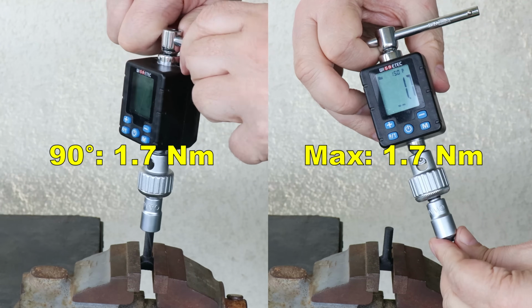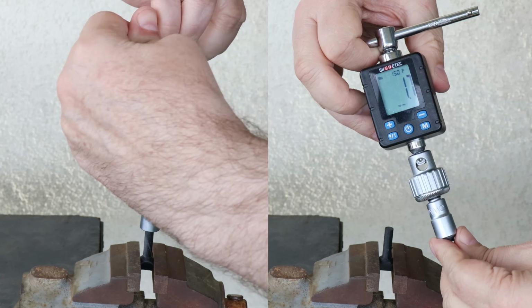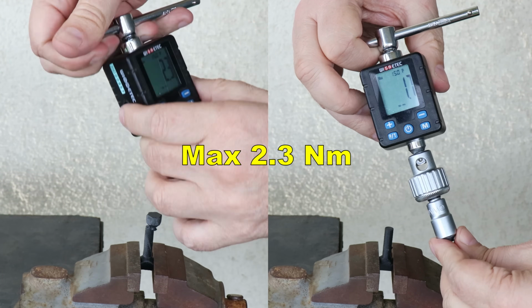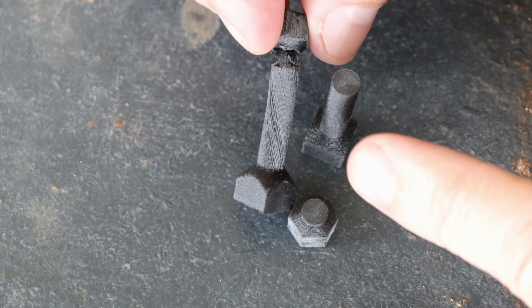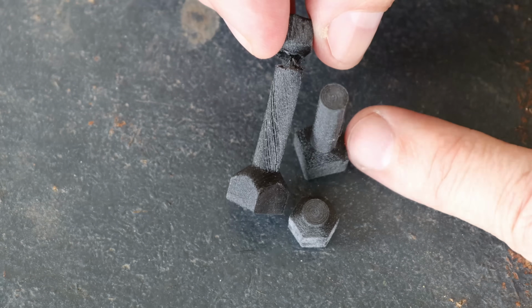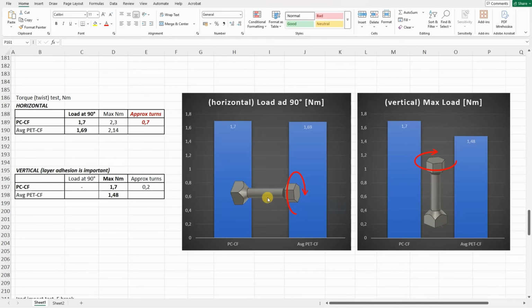1.7 for horizontal, loaded 90 degree rotation. And the maximum load, 2.3. As always, very similar numbers, but different break types. Printed in horizontal position, very similar loads at 90 degree rotation. Printed vertically, the PC-CF is stronger compared to the average PET-CF, but here I have a reduced number of test objects because I started this type of test much later.